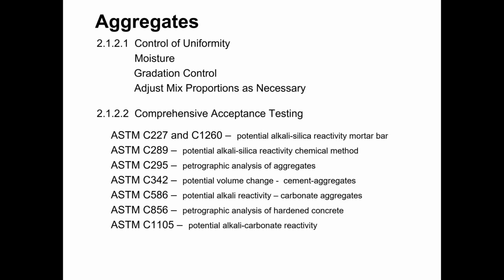We want to make sure that for any variation that we encounter, that we are making appropriate adjustments to our mix design. The most common adjustment to our mix proportions is going to be due to moisture. If we have a shift in the gradation of the aggregate or a shift in the fineness modulus of the aggregate, then we may need to adjust our mix proportions. That does happen, but that is much less frequent than the adjustments we would make for the moisture variation within our aggregates.